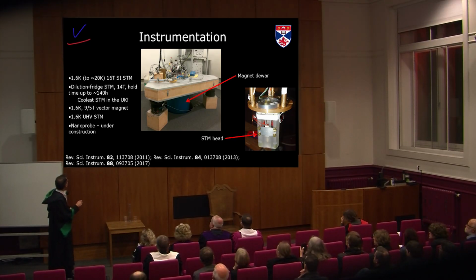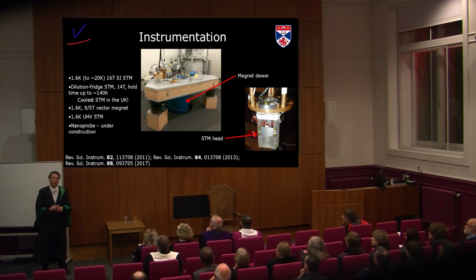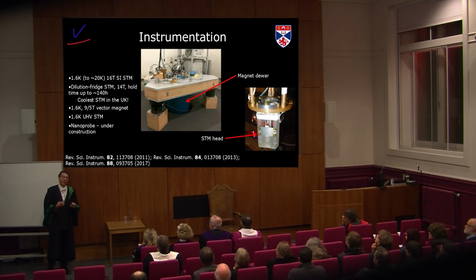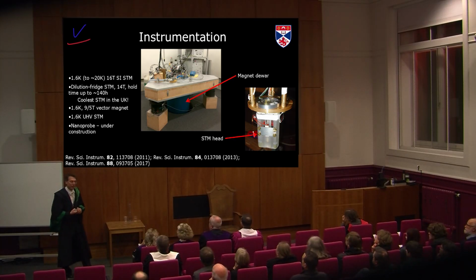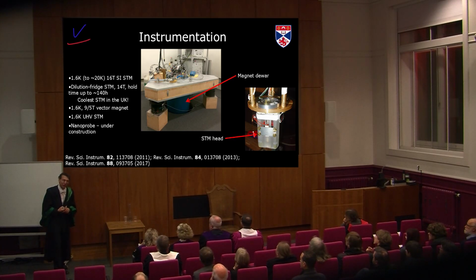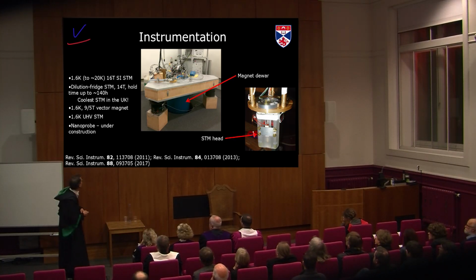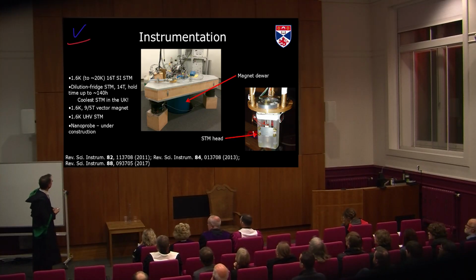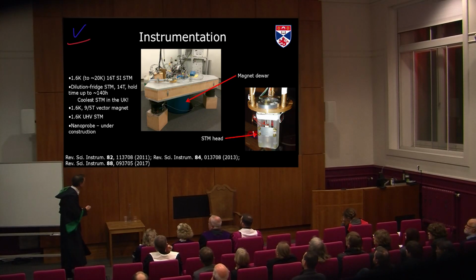And one of these is in a dilution fridge. It can cool the samples down to a temperature of below 100 millikelvin. So that's below minus 273.05 degrees Celsius. So it's less than 0.1 degree above absolute zero, above the lowest you can achieve in the universe. And so I think up to now it's probably still true that it's the coldest STM in the UK.